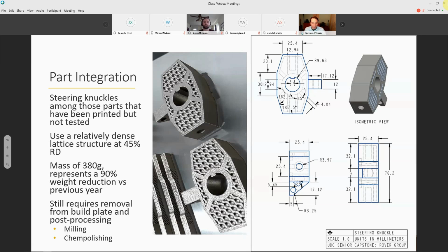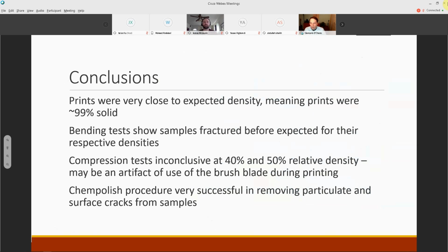And we still need to remove these from the build plate, conduct milling to clean the face of the part, and then chem polishing to remove the metal particulate, particularly in the lattice structure itself. So we found that our prints are very close to the expected density according to the manufacturer's specifications. So a little more than 99% solid, which is pretty good for a powder bed printer.